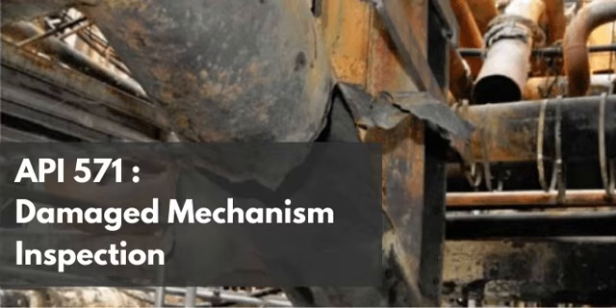The pipe is fine, but the text highlights a massive counterintuitive vulnerability when you actually have to weld those pipes together. Because welding 300 series stainless creates a completely unique metallurgical problem. Let's explain why that is. Well, when you weld 300 series stainless steel, you are obviously melting the metal. Right. As that weld pool cools and solidifies, if the resulting weld deposit is purely 100% austenitic, it is highly prone to microscopic tearing. Tearing as it cools. Yeah. The thermal contraction stresses during solidification actually cause the grain boundaries to pull apart. Yikes. It's a severe fabrication defect known as hot cracking. And you obviously cannot put a pressure vessel or a high-temperature pipe into service if the weld seams are full of microscopic cracks. You absolutely cannot.